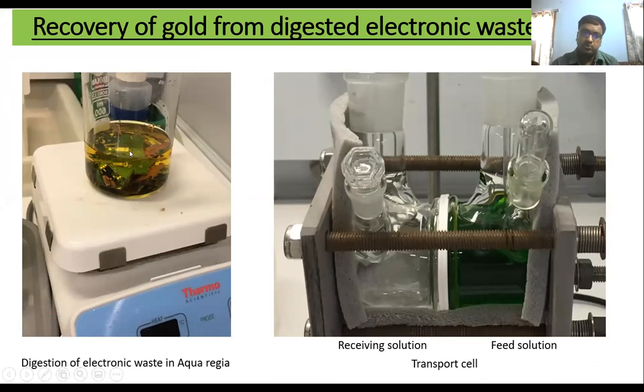So what we did is optimize these two membranes, and we used those membranes for the 6 molar acid as well. In this case, we took some old mobile phone. We got the electronic part and put it in a glass beaker. Then we poured some aqua regia solution over it and heated the solution. After heating, all the electronic parts dissolved in the solution. We filtered the solution and put it in this feed solution. So this is our real solution. If you digest all the electronic parts, we get this solution.